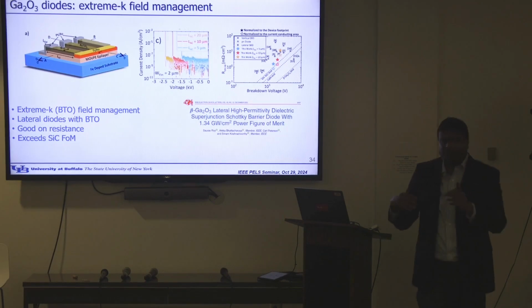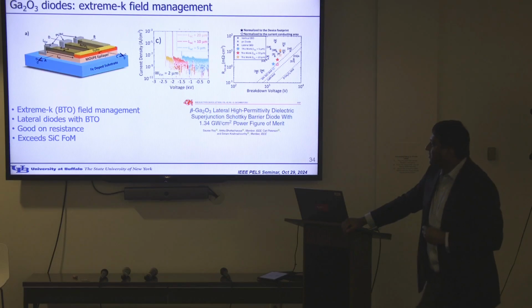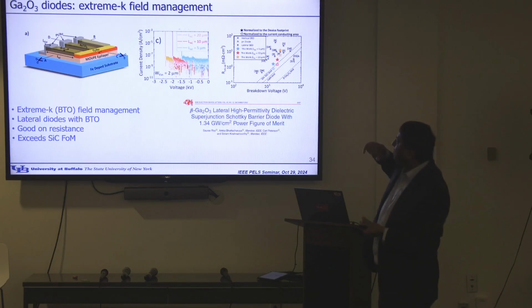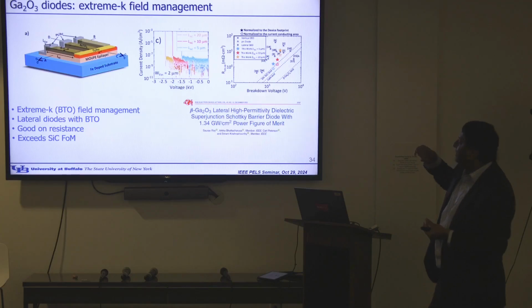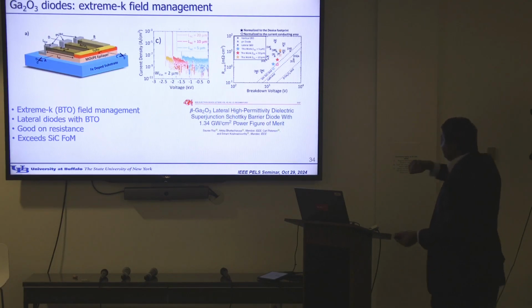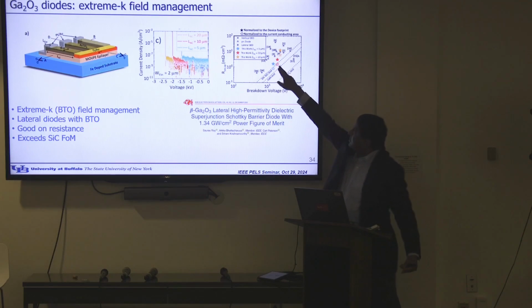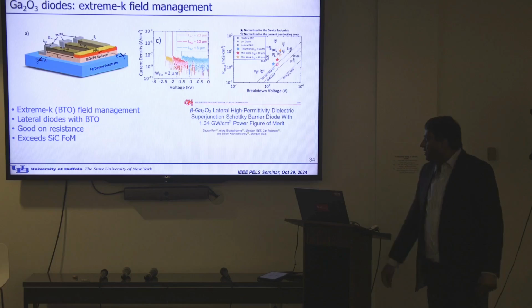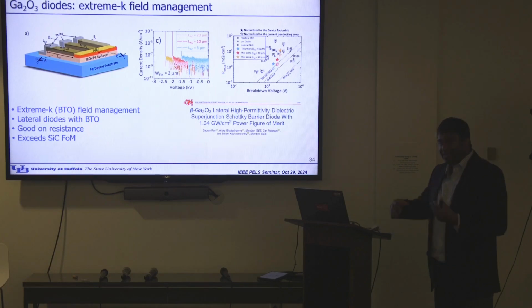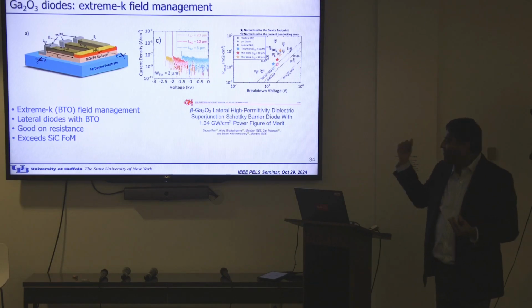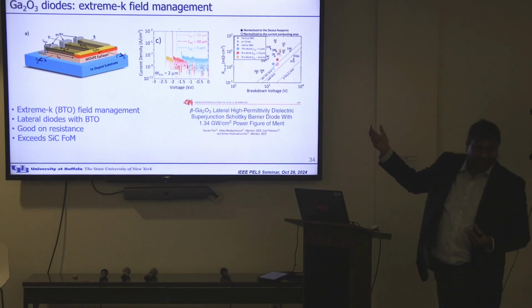Another area that actually came out from gallium oxide, it came out from Ohio State University, Professor Rajan's group, is using extreme K or barium titanate for field management. This actually came from the need to manage fields in very high breakdown devices, and this is showing a lateral device using barium titanate for field management, and you can see that they're able to achieve, in single devices, beating silicon carbide numbers, right? So again, what I was trying to show is that TRL level 3 single devices have been demonstrated conceptually, experimentally, sorry, and then they do exceed the silicon carbide performance.